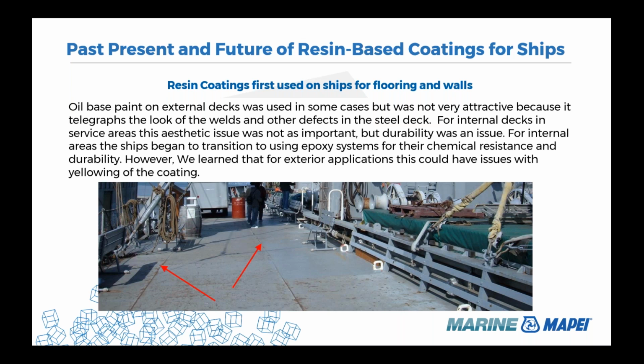They started to shift in those areas to using epoxy-based systems because they gained abrasion resistance and chemical resistance, so you had better durability. But for exterior parts of the ship, they found that these coatings could have issues with yellowing if the coating were exposed to the sunlight.